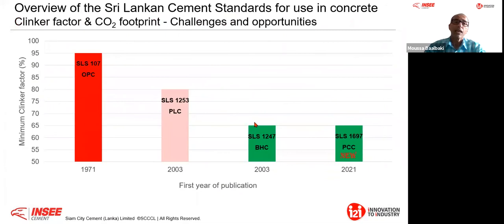Now I have talked about how to mitigate CO2. How to mitigate CO2? I mentioned the clinker factor. The clinker factor is really important here. When I look, for example, at the first year of publication of all these standards, the OPC was first published in 1971, where we know the carbon footprint is around 1 ton of CO2. After that, it took almost 30 years before the blended cement, either Portland limestone cement or blended hydraulic cement, came; we got this standard in 2003. Therefore, we had 30 years where all our engineers' and projects' experience was built on the OPC.